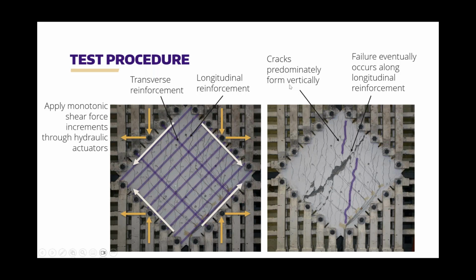And so as you'd expect, the cracks predominantly form vertically in the panel. And so those are in the direction of the principal tension. And then you eventually get failure along the longitudinal reinforcement. So that's what you see in the big crack there. That's the final failure surface, which happens along that longitudinal reinforcement.